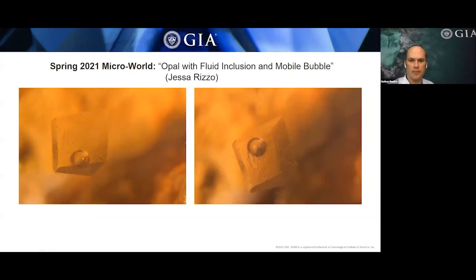We also had a mobile inclusion in an opal for this section of Microworld. And fluid inclusions in general are quite uncommon in opal. But what happened in this case was most likely there was a barite crystal that was trapped within the opal and then subsequently dissolved away, perhaps a crack or something allowed fluids to come in and dissolve that barite inclusion away, leaving this barite shaped void. And as the fluids dissolved it away, the crack was potentially rehealed, trapping some of that fluid inside the void. So now you have a space that's large enough for this bubble to mobilize and move around as you rock and tilt the stone. So quite an interesting inclusion in opal.